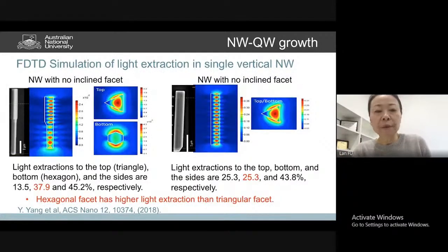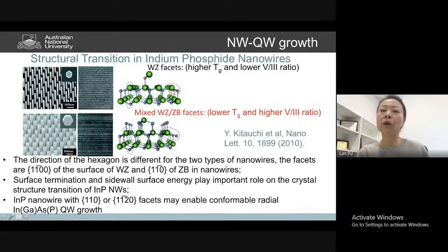Of course, we're not stopping there, because if we carefully look at the simulation results again, comparing the light extraction from the top triangular shape and the bottom hexagonal shape, we found that certainly the hexagonal shape, some facet somehow helps the light extraction. Then it's quite ideal to make hexagonal shaped nanowires. So that's what we want to do next. So how have we really transformed that triangular facet into a hexagonal facet?